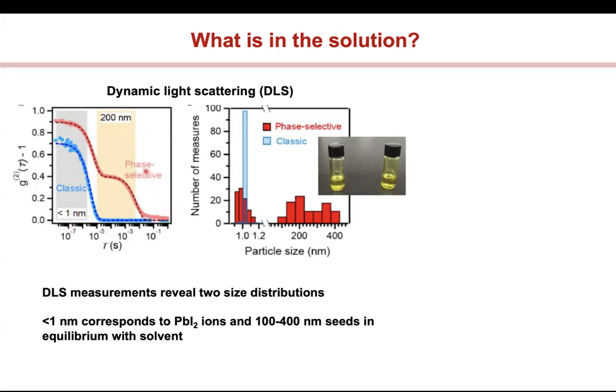Whereas in the phase selective method, where we added these crystals, now what you start to get is two distributions. So you have the first distribution and the second one. The first one matches that of this lead iodide. Obviously, there's lead iodide in the system, but the second one gives you a much larger distribution, of the order of 200 to 400 nanometers. So you have these crystallites which are in the solution. These are colloidal things which are stable in this solution. Okay. And so this is giving you something very different, which means that these crystals that we added into the solution somehow have found a way to remain stable in the solution. They don't completely dissolve. Okay.